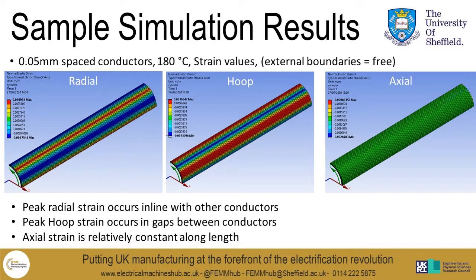So this slide shows some sample results obtained from that model. In this case, the spacing between the conductors was 0.05mm. A 180-degree temperature was applied, and this shows the strain values which were obtained. So you can see when you consider the conductor, the radial strain peaks in line with the other conductors in the model, which is the opposite of the hoop strain, which peaks in the gaps between the conductors. You can also see that the axial strain is relatively consistent across the length.